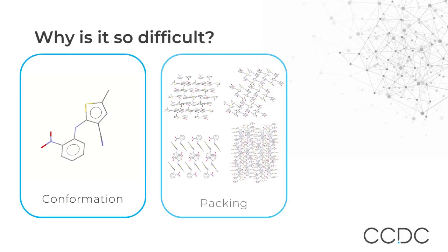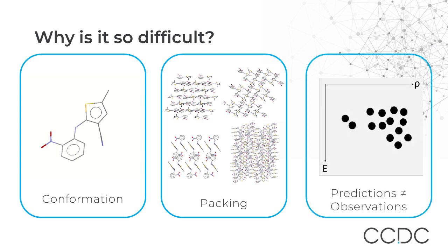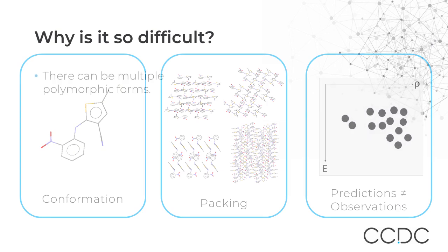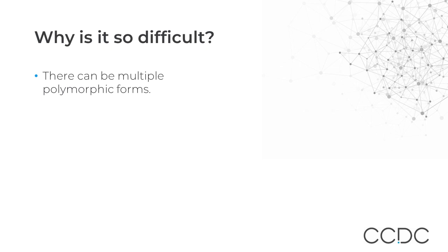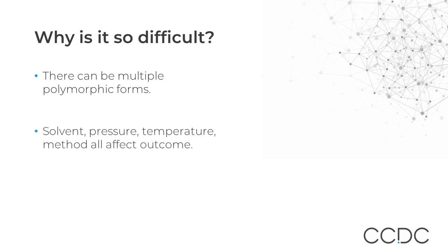Even if software can predict the conformation of a molecule observed in a crystal, we still have the challenge of predicting how that molecule packs. We need to sample many space groups and unit cells to achieve this. We could generate a landscape of plausible structures and rank them on their energy, but the lowest energy structure is not always the observed structure. Maddox's original view to predict the structure was naive — we have to predict multiple structures since we have multiple different polymorphs, stable and metastable, which form under different experimental conditions. Experimentalists can vary solvent, pressure, temperature and crystallisation method to get alternative forms.